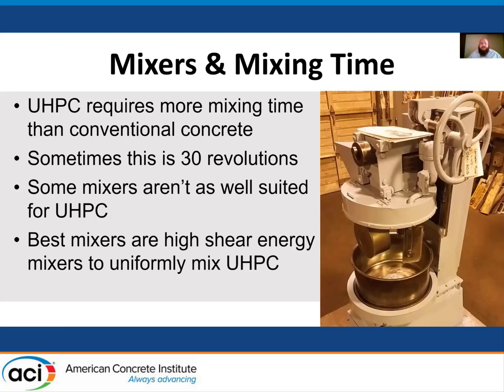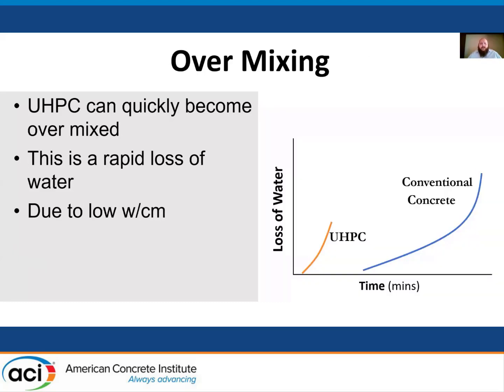So when we talk about mixers and mixing times, I believe there's another speaker right behind me that's going to talk a little bit more. But in essence, you're trying to get that water all the way through all that powder and all that sand, and that's a lot of surface area to get there. Sometimes it takes 30 revolutions more than a conventional mix. Sometimes it takes more than that. Sometimes there are mixers that just aren't as well suited as others to produce this UHPC product. Typically you want something that has a high shear energy mixer, and you really want something that's going to provide a good uniformity to the mix. That's kind of the goal.